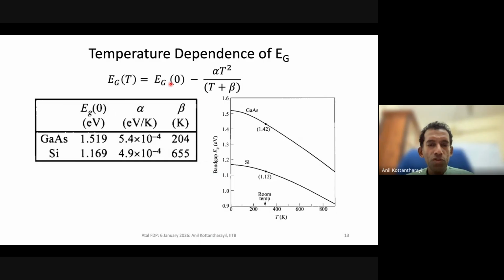The band gap is also temperature dependent, and that's a very important consideration. You can see as the temperature increases, the band gap decreases. That is important because the efficiency of solar cells also decreases with increasing temperature, and that can be traced back to the temperature dependence of the band gap. For common semiconductors, this is true. But more recent ones like perovskite show a slightly positive temperature dependence of the band gap, so the band gap increases mildly with increasing temperature.